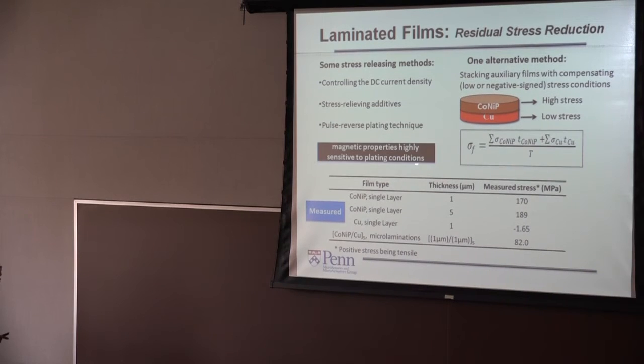One alternative way is to stack your targeted film with some auxiliary films that have compensating stress conditions, for example a low stress or a negative stress condition. Studies show that for a multilayer structure, the average stress can be represented as an individual-layer weighted stress, under the assumption that your multilayer is thin and everything runs in the linear elastic regime. So we want to understand whether this formula applies to our system.